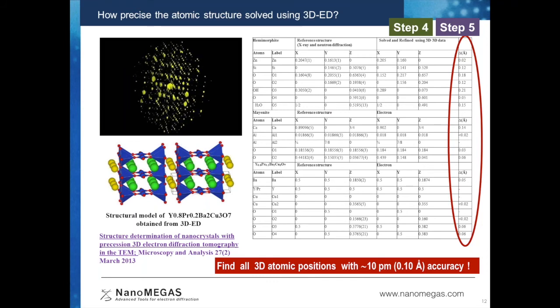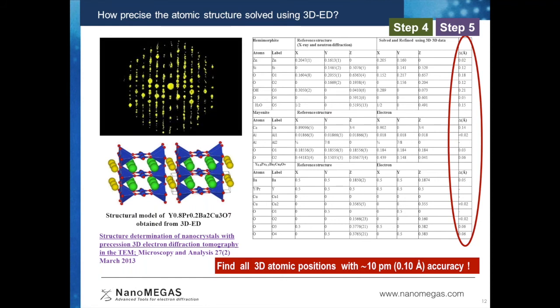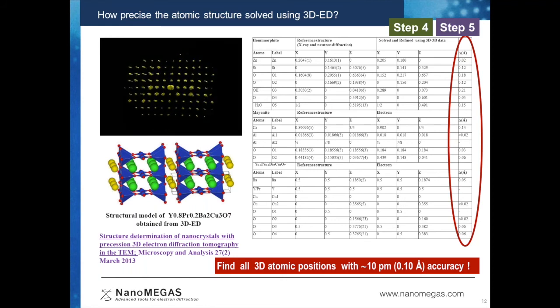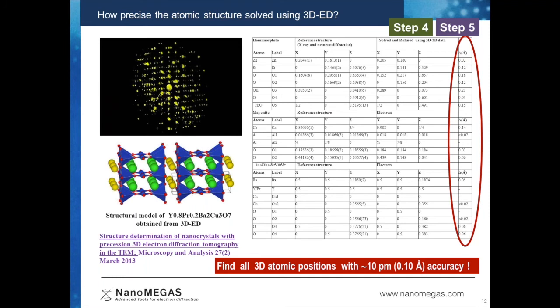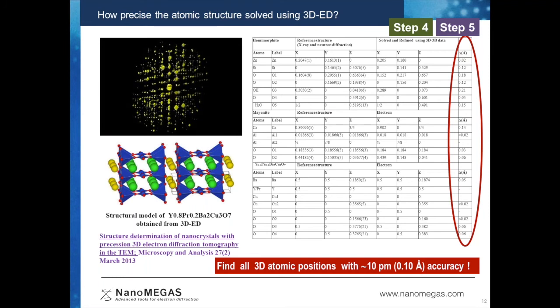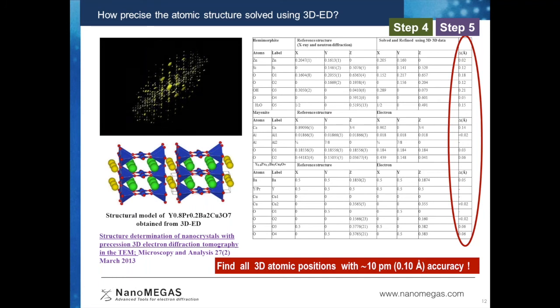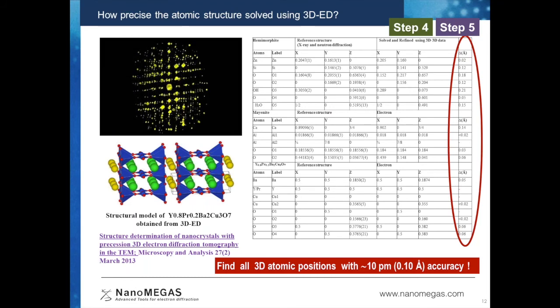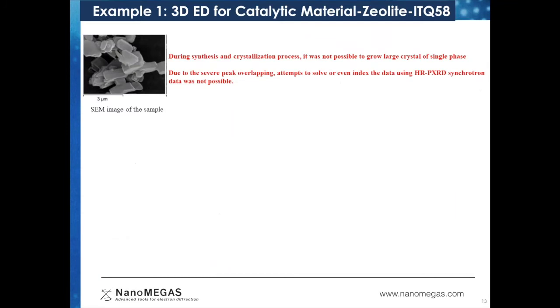In the last column, marked in red, you can see the difference between the atomic coordinates of the structures solved by electron diffraction and structures solved for the same material by single crystal X-ray diffraction. And you can see that by doing a structure solution from 3D electron diffraction data and doing a kinematical refinement, one can get a structure of 10 picometer accuracy, or 0.1 Angstrom accuracy.